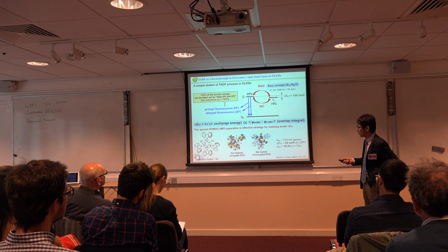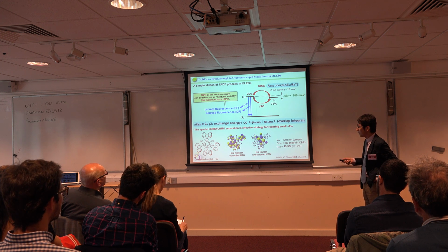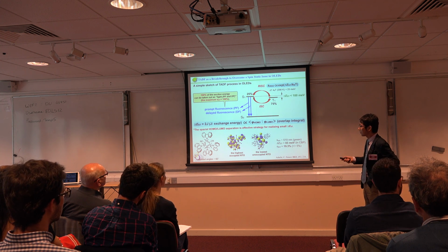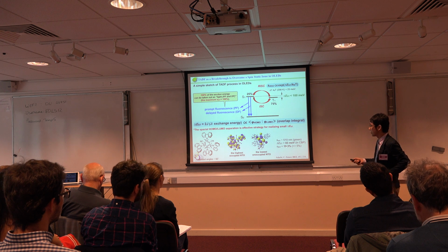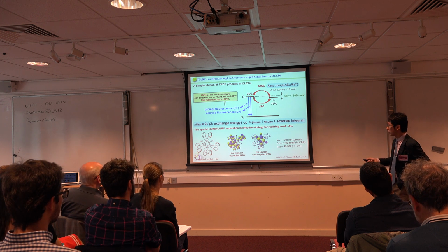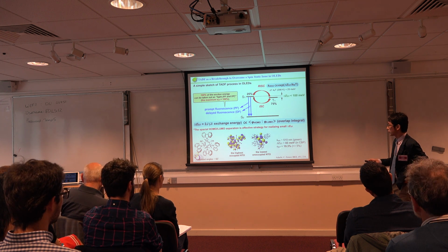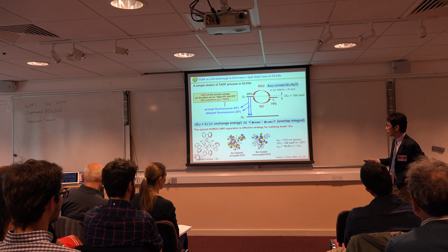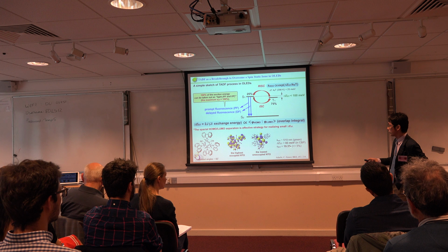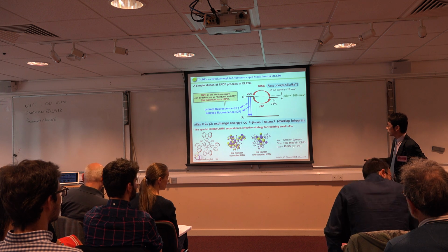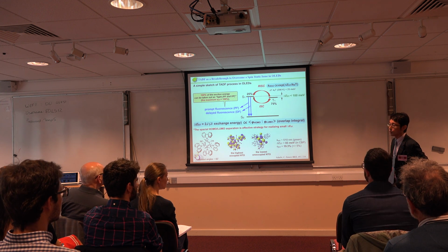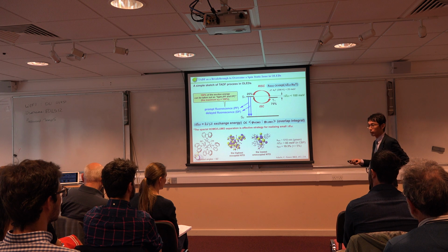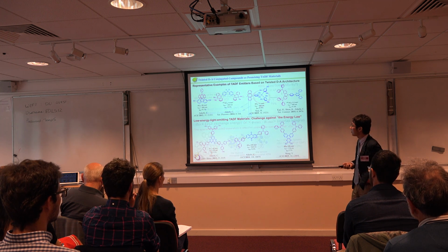Actually, in this molecule, the HOMO and LUMO are effectively separated, giving a very small delta EST, and the external quantum efficiency is very high, higher than the theoretical maximum value of conventional fluorescent OLEDs, 5%.